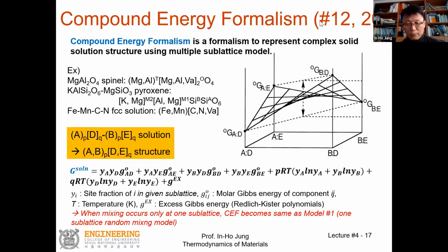Also, when we defined the quasi-chemical model, we defined the coordination number. For example, for the FCC solution, theoretically we have to use coordination number 12 because the number of nearest neighbor atoms in the FCC is 12. And last time I also showed you the coordination number in liquid magnesium and tin alloys, the liquid metallic solution. Theoretically, the coordination number in liquid alloys is about 10, so it's between BCC and FCC, more or less.